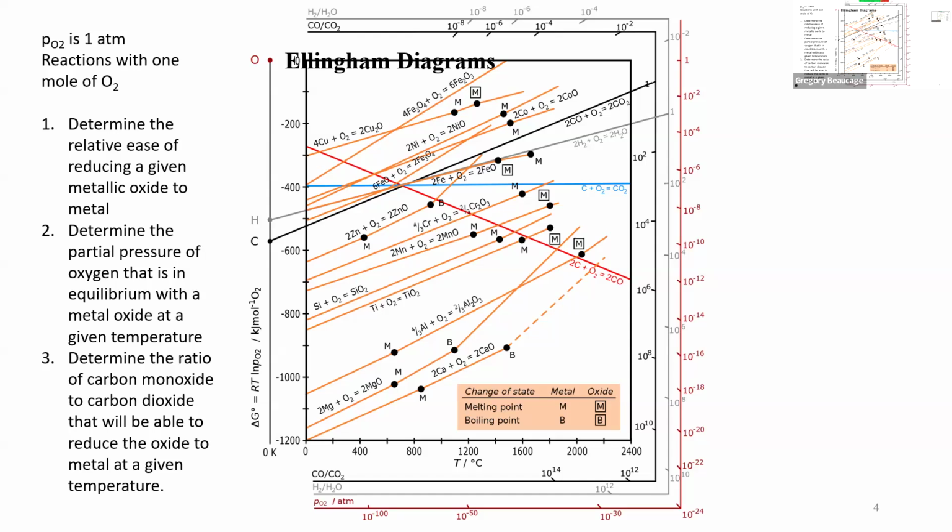No O's. You have to remove the O somehow. You have to reduce it. So you can do that by mixing the two together with magnesium, and then because this is easier to reduce, magnesium metal will pull the oxygen off the silica, make silicon, and make magnesium oxide with some other byproducts of the reaction. But you can use the plot to just determine the temperature and see.